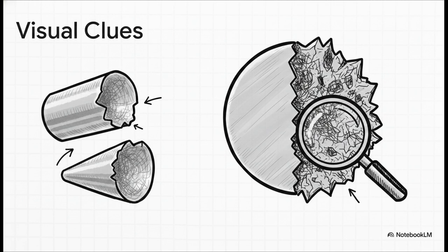But the absolute biggest clue for fatigue failure is seeing 2 highly distinct zones on the exact same broken surface. Usually you'll see a really smooth, almost polished area. That smooth zone is where the crack was slowly growing, and the 2 sides of the crack were literally rubbing against each other over time. But right next to it, you'll see a very rough, jagged zone. That rough area, that is the final fracture zone. That's the part that tore apart instantly when the remaining metal just couldn't hold on any longer.